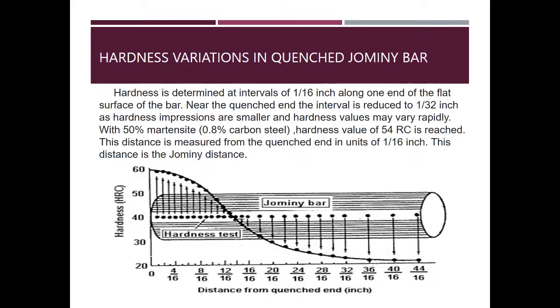Hardness variations in the quenched Jominy bar. Hardness is determined at intervals of 1/16 inch along one end of the flat surface of the bar. Near the quenched end, the interval is reduced to 1/32 inch as hardness impressions are smaller and hardness values may vary rapidly. With 50% martensite in a 0.8% carbon steel, the hardness value of 54 HRC is reached. This distance is measured from the quenched end in units of 1/16 inch. This distance is the Jominy distance.